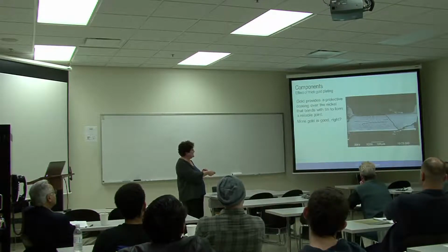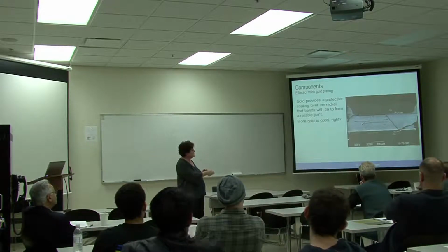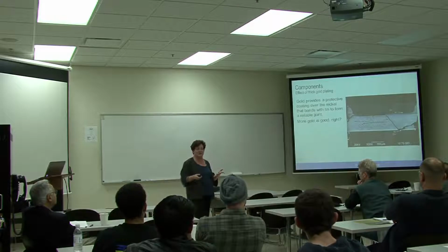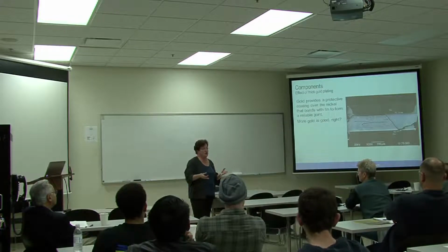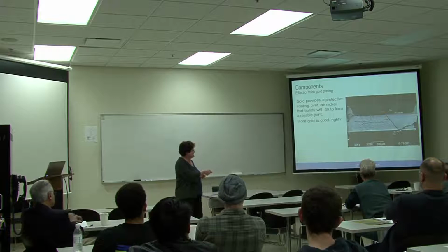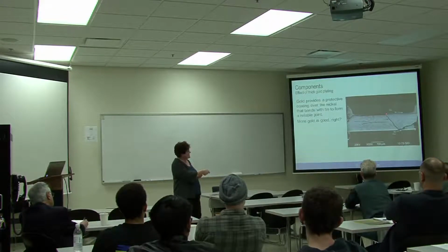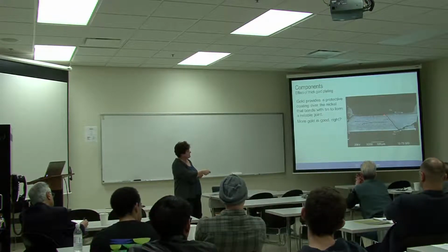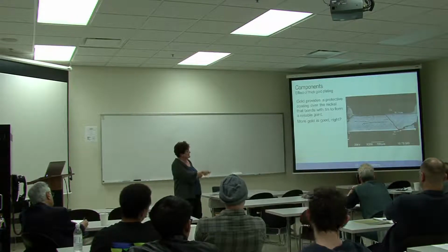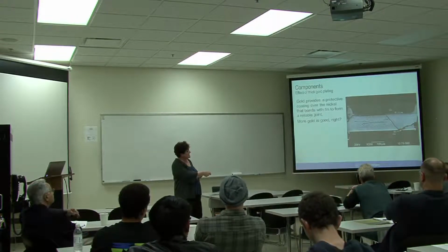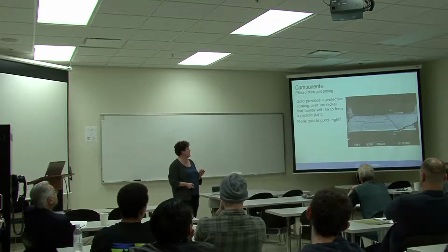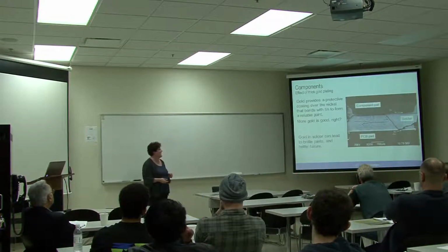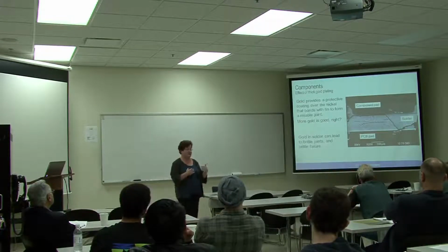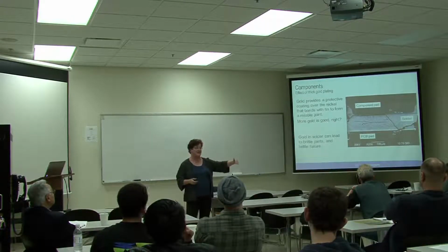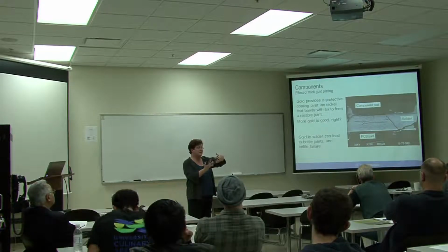When we do aging, it starts to actually move. It moves down and settles along the surface there. And so what you get then is a tendency to crack either in shock or in thermal cycling. You'll get a tendency to crack along there. So you can see that this is followed along the gold tin intermetallic that accumulated at the surface. It's followed along a big grain, a needle that went down this way, and then it followed another needle that went up there. So too much gold is not good. And it leads to a brittle failure as opposed to a ductile failure. It's a very straight-edged kind of failure. It's not the ripping, tearing kind of look to it.